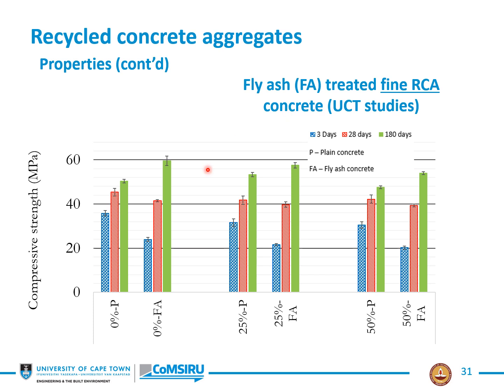And here again, compressive strength, and you see 3, 28, and 180 days. Again, you can see that at 180 days, really, there's not a lot of penalty to pay. In this case, using 50% fly ash, a 50% replacement, in a fly ash concrete. And you can see the same in the early strengths, a little bit lower here.